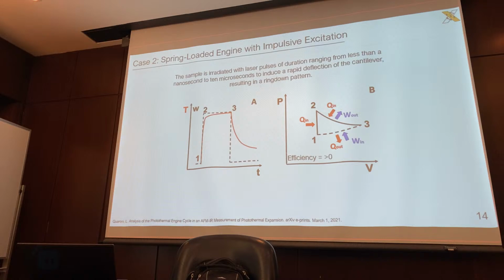And so you can see how this might correlate quite strongly with the coefficient of thermal expansion. Because say if your pulse width is too short, your sample will not reach the maximum temperature and eventually the maximum deflection. So I will explain later on why this actually weaves into some of the research that we've done regarding pulse width.